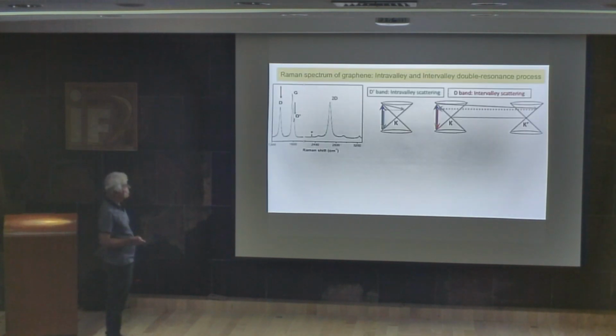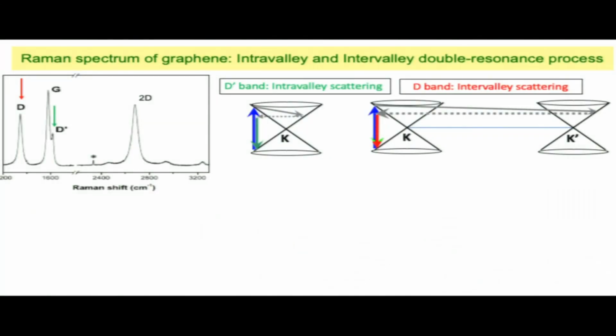And why does it occur? For example, now I'm showing the Raman spectrum of a bad sample of graphene, disordered graphene with defects. Then we have more than the G and the 2D bands, we have the D and the D prime bands, which appear only when I have defects. And the processes for the D and the D prime are very similar to the case of the 2D, but in the case of the 2D, you remember that I have two phonons, but now I have one phonon. First we have a creation of one electron-hole pair. The electron is scattered from this point to that point, to the K prime, but then the defect allows the electron to scatter back from the K prime to the K. And this kind of thing is elastic scattering.